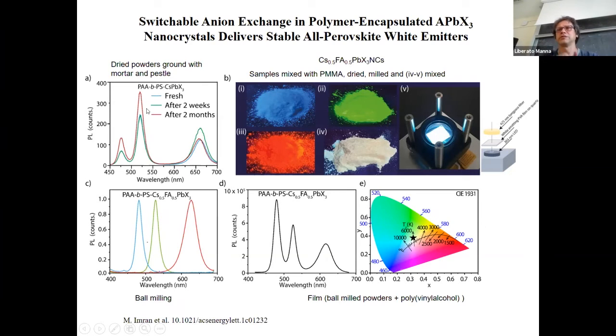Okay, so now you can make powders of these nanocrystals, for example. You can grind them simply with a mortar and pestle and mix them together. When the powders are dry, the polymer is in the globule state, so there is no inter-nanocrystal anion exchange. So this mixture of powders preserves their colors of emission, the multicolor emission, over months. You can do something even better.